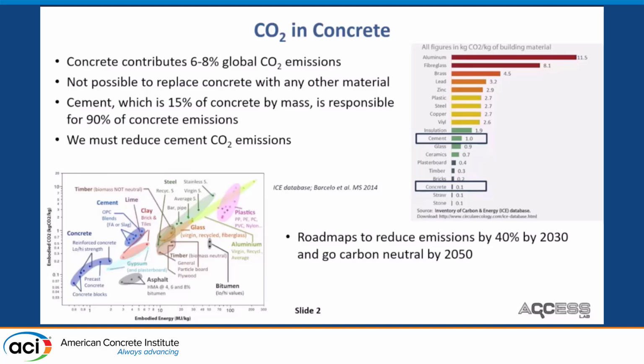Although it has to be acknowledged that cement, which is only 15% of the concrete by mass, is responsible for a significant proportion, 80 to 90%, of concrete emissions. So it's pretty straightforward that we must reduce cement emissions. And these days, everyone has a roadmap, and these roadmaps ask us to reduce our emissions by 20, 30, 40, 100% in the next X, Y, Z years.